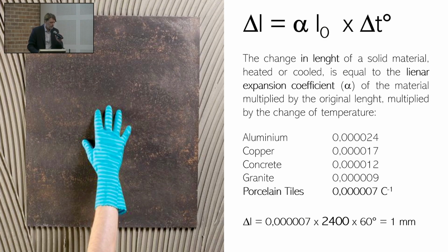Is 1 millimeter a big deformation or not? I would say that 1 millimeter is not a big deformation, but you already know what happens when I fix 10 tiles. I will not fix one tile. I will fix 1, 2, 3, 4, 5. And if each of them has a deformation of roughly 1 millimeter, maybe less, maybe more, the 10th tile will be pushed away from the surface because they push each other.